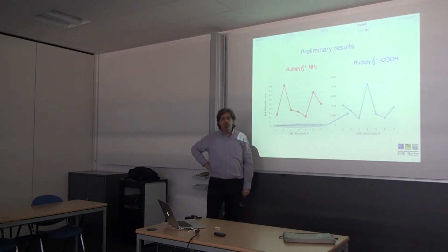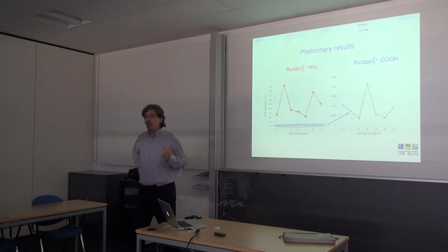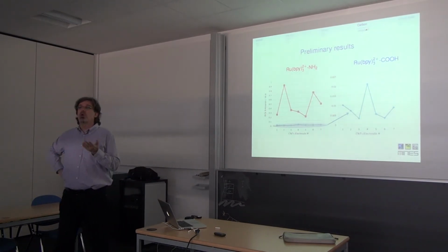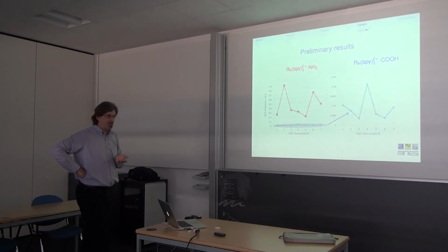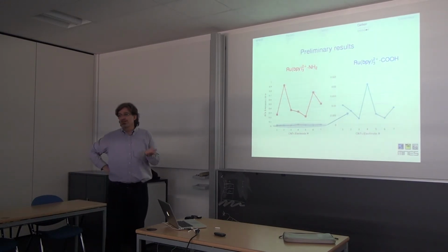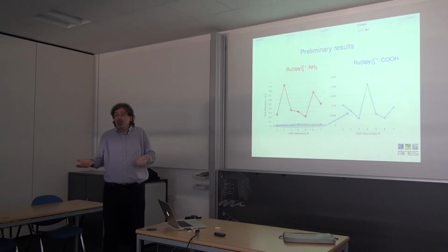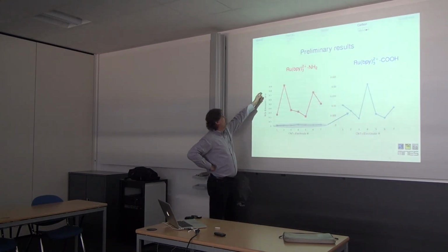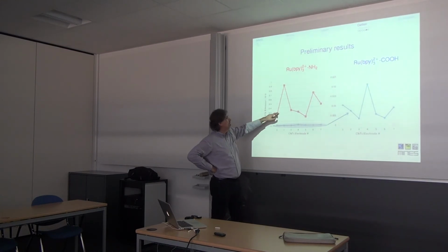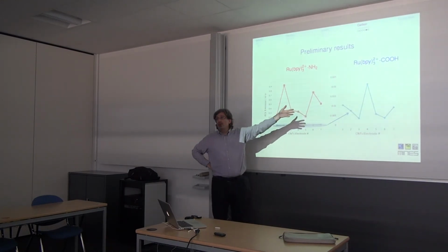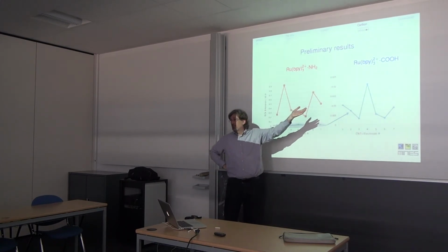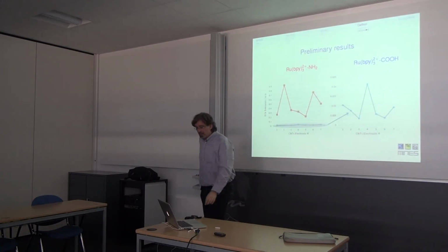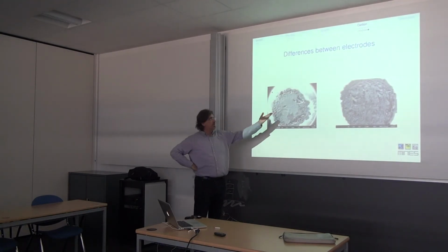7 different electrodes. From these plots, I have the bad point of this technique. The reproducibility is a mess. The reproducibility is very, very, very low. Here we are talking of an emission in an arbitrary unit because it's normalized, but 0.9, 0.2, so it's unreproducible. Because your electrodes are all different. Look at the surface.